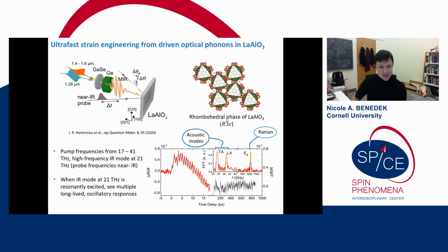So what was done in this experiment was that a pump was tuned to frequencies from 17 to 41 terahertz. There is an IR active mode at about 21 terahertz. And when that mode is resonantly excited, then there are multiple long-lived oscillatory responses. This inset is the Fourier transform of this reflectivity data.